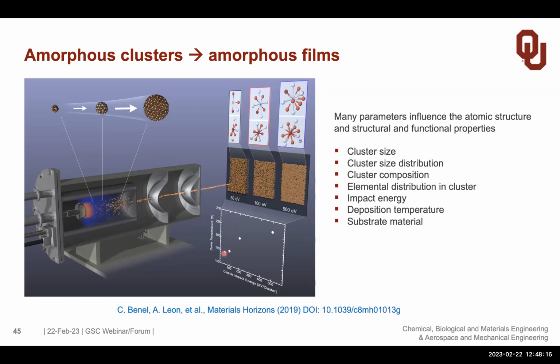Moreover, we also see that the magnetic property, the magnetic ordering, is changing, and this is characterized by the Curie temperature, which is the transition temperature between ferromagnetic and paramagnetic behavior. It changes about 60 degrees depending on how we deposit the clusters. And incidentally, if we use 500 eV, that's a very high energy.